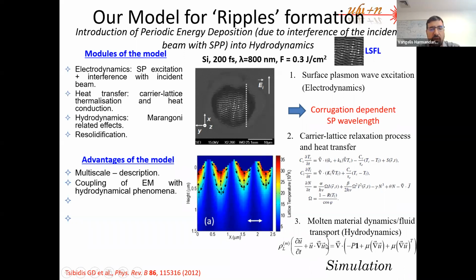There you have a molten material, as you say, molten material dynamics, but is the temperature constant? No. It's not. I'm just trying to understand the temperature, because as you say, you have a two temperature model, but I assume that in practice you would have a gradient of temperatures. You see here, this is the profile, this is fluid. And you see a gradient of temperature. We have the Navier-Stokes and these parameters, the density and viscosity are temperature dependent. When I say temperature dependent, lattice temperature dependent. So you can envisage that the two temperature model becomes a single temperature model when the relaxation occurs. So the electron and the lattice system have the same temperature.